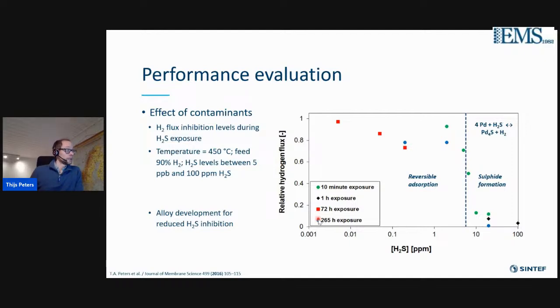Here you typically see the effect of contaminants, where we exposed palladium silver membranes to different levels of H2S. And there you can see that depending on the H2S level, you are either in the reversible adsorption range or in the range where sulfides are being formed, and that should be prevented. So irrespective of whether the membrane is exposed to H2S for many days or only for 10 minutes, basically the palladium membrane is destroyed if it's exposed to more than 10 ppm of H2S. This is important information for process integration.